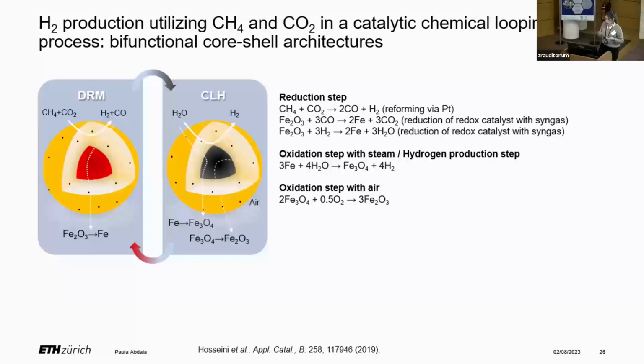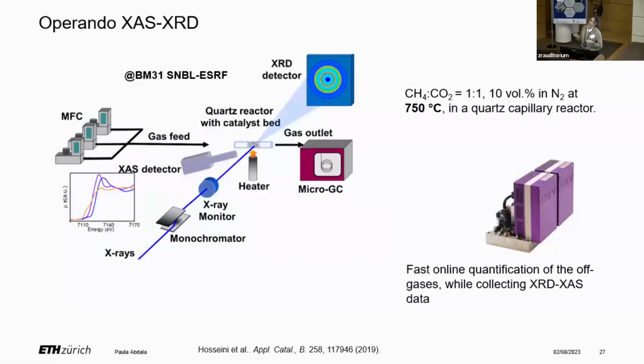We brought this to the Swiss Norwegian beamline again, and we followed the processes during the reduction stage with dry reforming of methane by diffraction, and also we did some EXAFS. But here I will show you mainly the diffraction due to time.